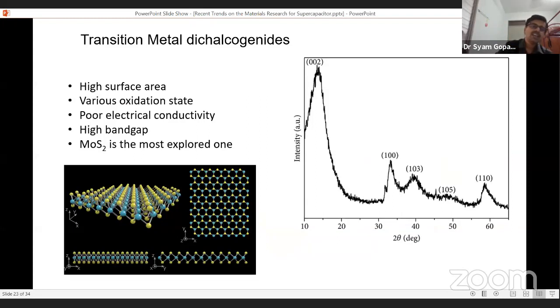Then another interesting material is metal dichalcogenides, which again has a layered structure. And the most explored metal dichalcogenide is molybdenum disulfide. The problem with this molybdenum disulfide is its poor electrical conductivity. So many research groups explored its utility just because of its structure, where electrolyte ions can easily enter into this particular material, so that its capacitance can be higher. But the problem is its poor electrical conductivity, because its band gap is very high. As its band gap is higher, the electrical conductivity is supposed to be lower.